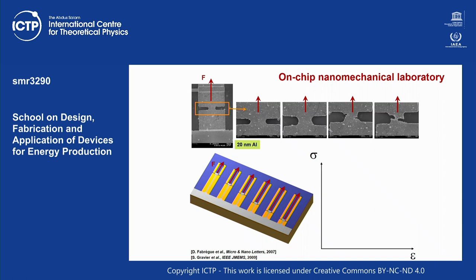Then we have here on chip, this is a top view, where we have, let's say, in blue, the material in which you have a lot of internal stress. And in gray, the material that we would like to test. And you have those two beams, and when you etch away by chemical reaction the so-called sacrificial layer, in that case the substrate, you can relax the internal stress that you have in these blue beams. Okay? And you have a uniaxial traction test on the material, which can be deposited at nanoscale.